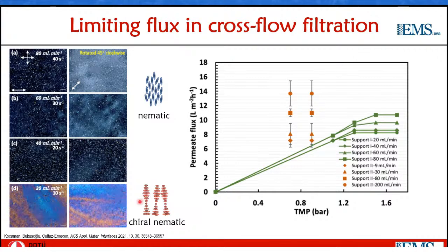And then because the half pitch of this twist is of the order of the wavelength of visible light, we see this multicolor appearance. So the highly concentrated cellulose nanocrystal deposit on the membrane exhibits chiral nematic order. And at the smallest flow rate, this order is not disrupted by the shear, but as the shear is increased, the nanocrystals start becoming aligned with the flow.